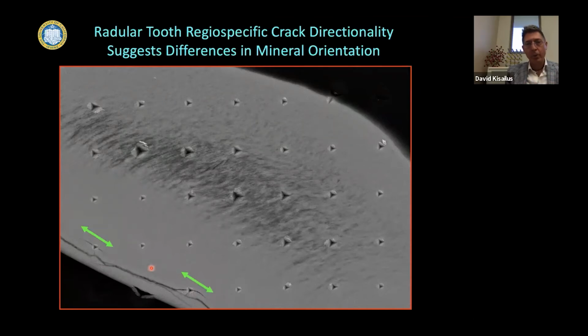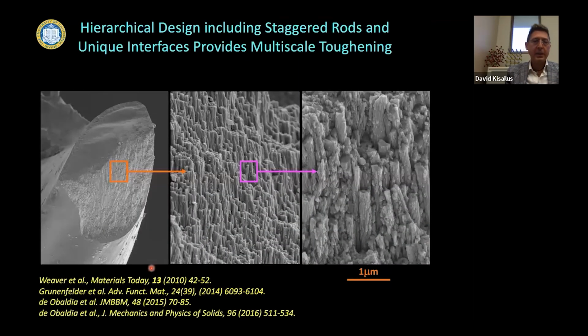We fractured open one of these teeth, and you can see in the shell region, the teeth actually contain nanorods of the magnetite material. And the nanorods are all oriented along the long axis of the tooth, actually providing some tensile strength, since as it's rasping, the leading edge will be under tension. But they're all oriented, and they're about 150 to 250 nanometers, depends on the location and the tooth diameter.